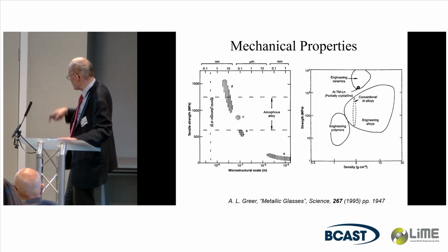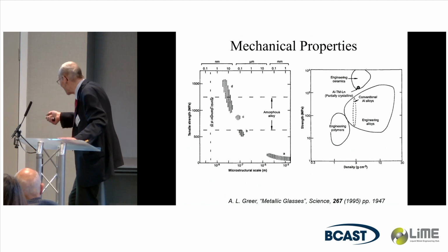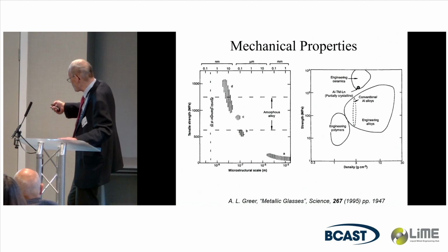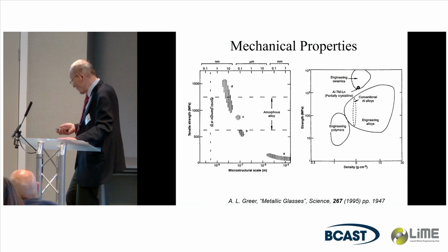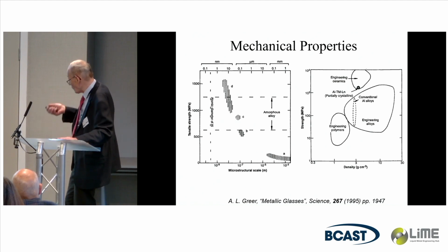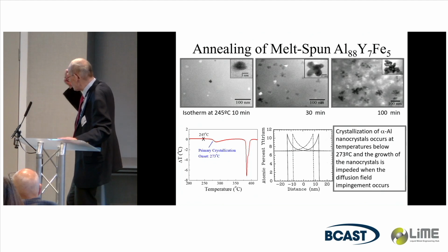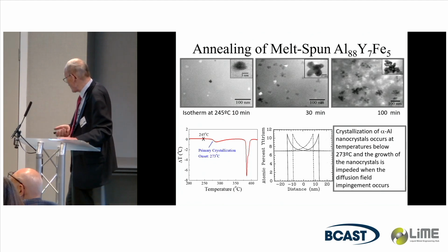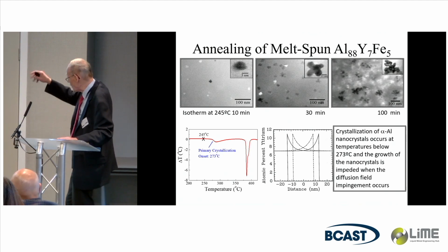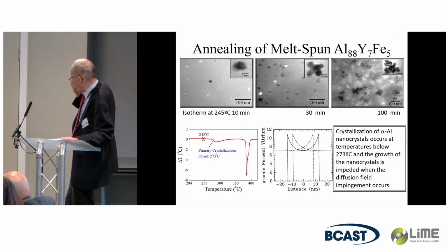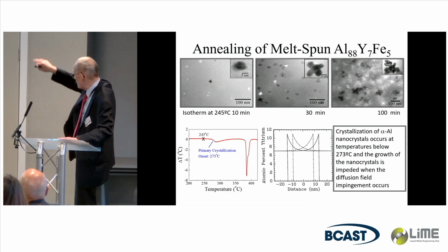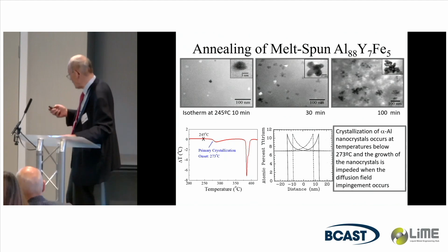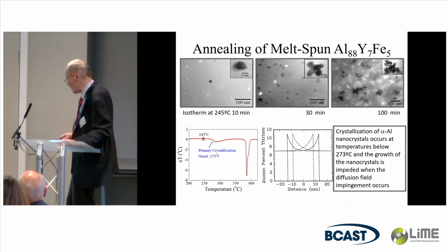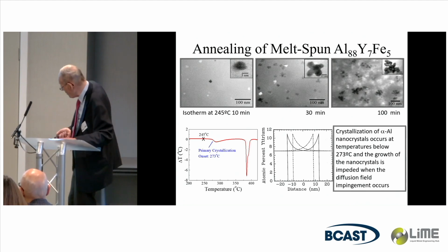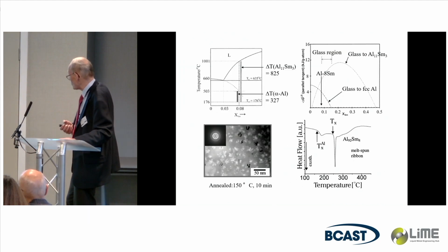amorphous alloys, when they're partially crystalline or nanocrystalline, actually go beyond the conventional alloy islands into the engineering ceramics. So these are very attractive, being lighter and stronger, and on a specific scale, approaching steels. And this is the typical crystallization reaction. The primary crystallization is one where you get aluminum in an amorphous matrix, and because of the very high density of nanocrystals and the rejection of yttrium and iron, the growth is inhibited so that you can maintain that size. And you can see before final crystallization, you have about a 75-degree temperature range up to about 350 or more. And that's pretty good for an aluminum alloy.